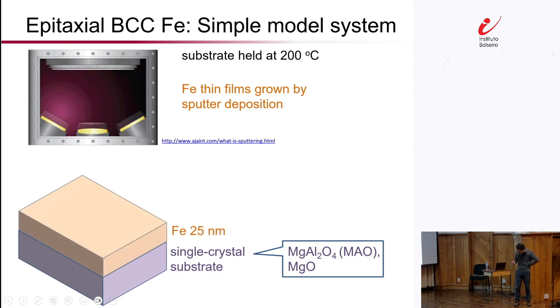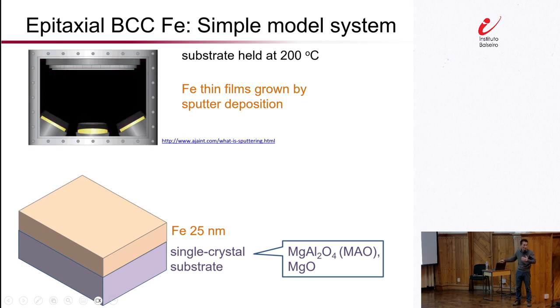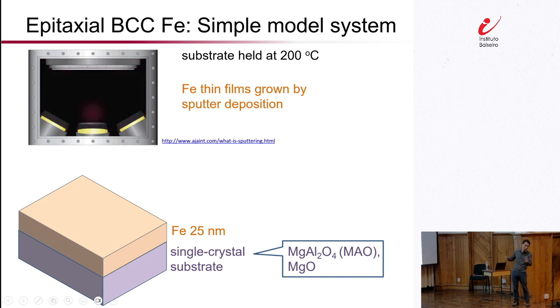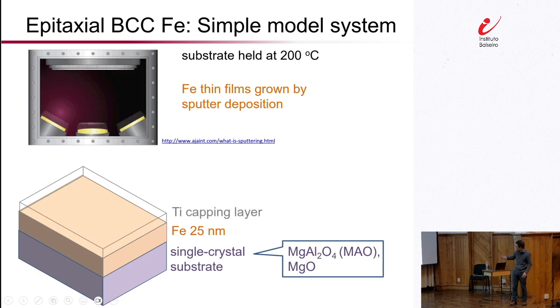Right. So in this presentation, I'm going to focus on just one thickness of iron, 25 nanometers. Turns out this is a very good thickness in the sense that it's not so thin that we have to worry about, let's say, some complicated things happening at the interfaces. So we're talking here about maybe almost 100 atomic layers of iron. And also, this is not too thick. It's not so thick that we have to worry about complications arising from, let's say, inhomogeneous excitation along the magnetic film thickness and so forth. But yes, we have looked at other thicknesses. And finally, of course, we have to protect the iron from spontaneous oxidation. So we have a capping layer of titanium.